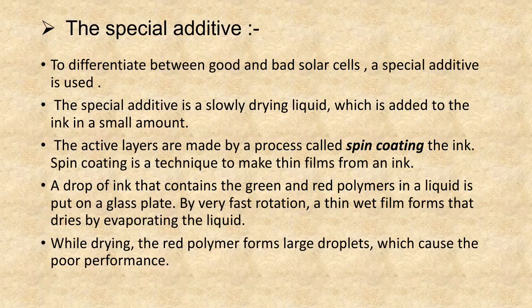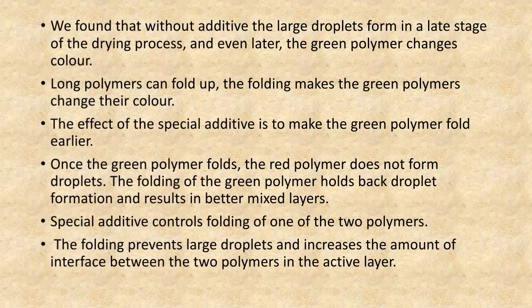The active layers are made by a process called spin coating the ink. Spin coating is a technique to make thin films from an ink. By very fast rotation, a very thin film forms that dries by evaporating the liquid. While drying, the red polymers, which are the shorter ones, form large droplets which cause the poor performance of the solar cell. We found that without the use of additive, the large droplets form in the late stage of the drying process.